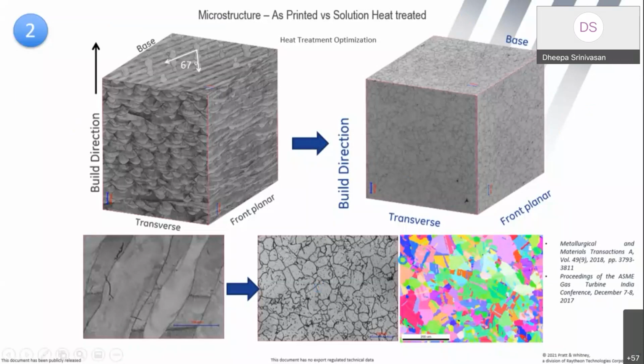So when we look at the microstructure, it gives a nice fine grain structure, not more than 35 microns. And here we're very thrilled about it, because fine grain structure means very good strength. But also we're a little worried, and that is challenge number 2 that I've highlighted here, because any fine grain microstructure is going to be a bane for creep response. This is going to be really bad. It's going to be creeping like crazy, because grain boundaries are diffusion paths, especially at temperature.